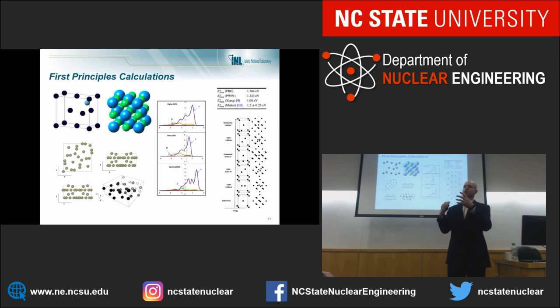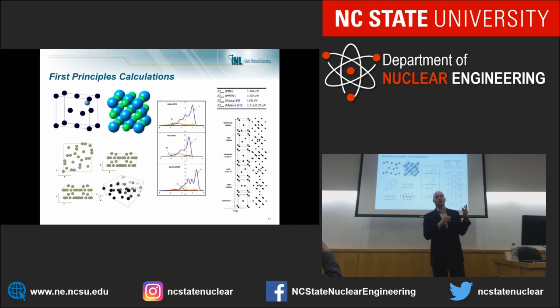So if you introduce a defect into these systems, you're going to have mechanical deformation of these systems. You're going to have decomposition of the crystal structure. So what you have to do is impose certain constraints on the number of atoms and which atoms are able to move and evolve, so that you can approximate what the defect formation energies are.